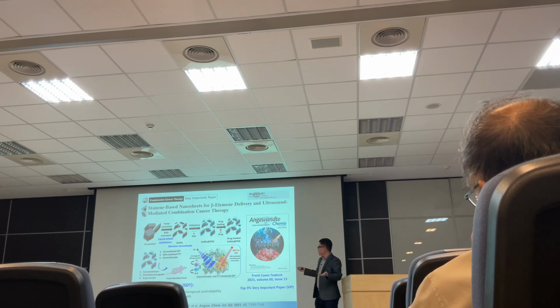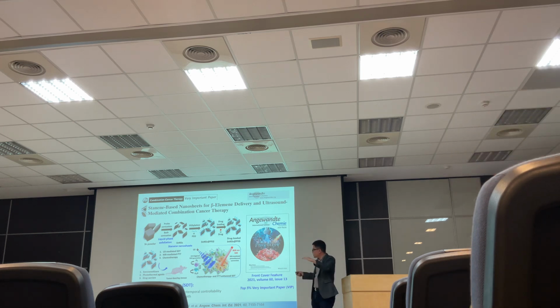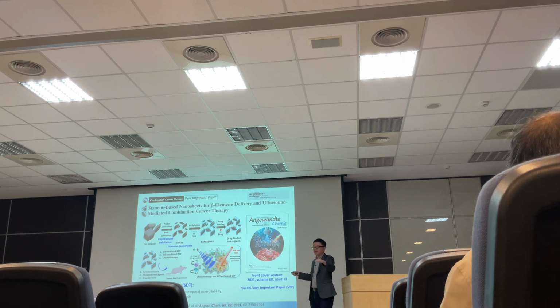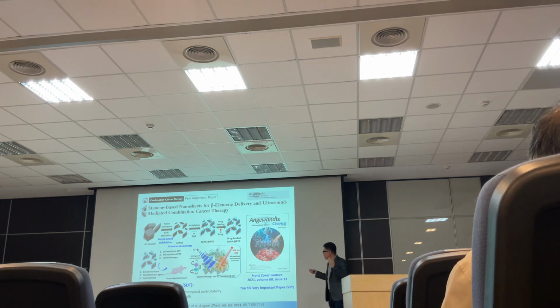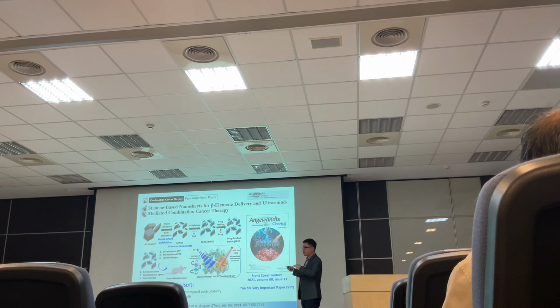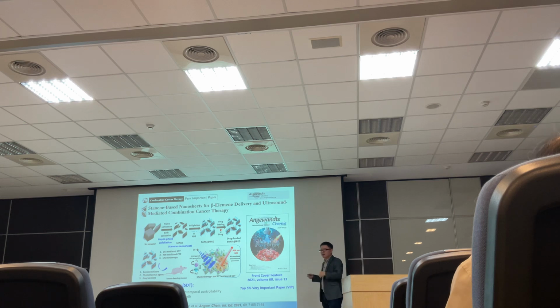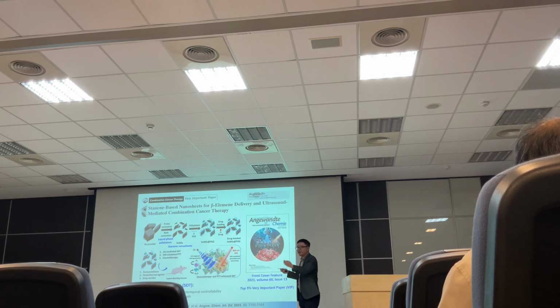Basically, we use a method called liquid phase exfoliation to exfoliate tin powder to make tin-based nanosheets, or stanene-based nanosheets. We can also modify these particles with PEG, a polymeric material, to make them more stable in the biological system. The primary reason for using 2D materials is that they have a very high surface area, so we can use it to carry drugs. For example, here we use a model anti-cancer drug. This drug is very hydrophobic and water insoluble, so we can use our materials to enhance its water dispersibility and increase drug bioavailability to the tumor cells.